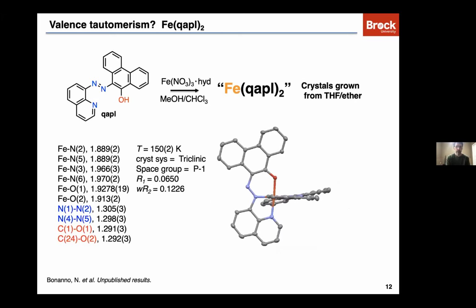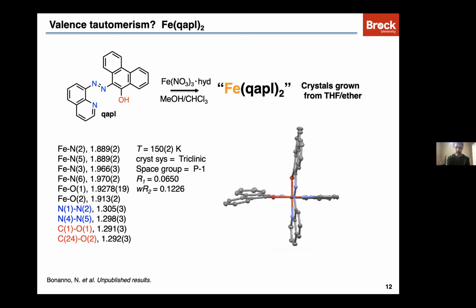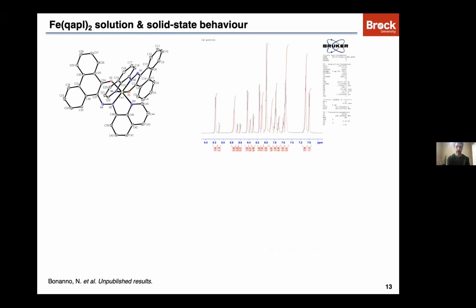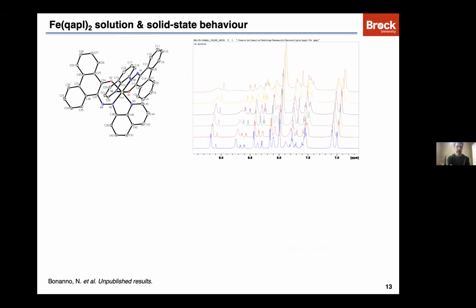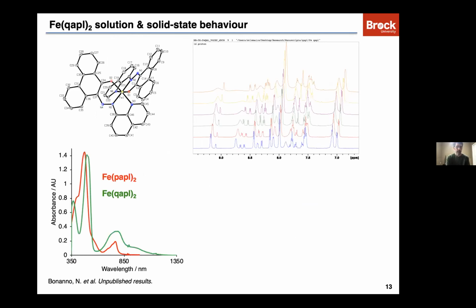So in solution, we see, there's another view of the crystal structure, just kind of rotated around. In solution, in the NMR spectrum, we see two sets of signals. And there's a temperature dependence, which kind of suggests that we have two diamagnetic species in equilibrium with one another. So one set of signals decreases in intensity and another one increases as we change temperature. And so what could possibly be going on here?